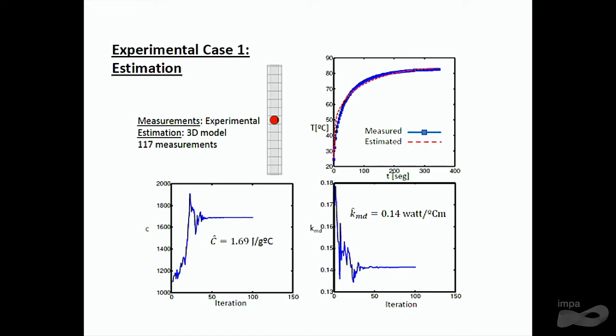The values obtained are close to the ones reported in the literature and the ones we have measured by independent means. This basically corroborates the validity of the model and essentially the assumption that we made, that only the particles that are in the cross section between the beam and the sample are the ones that produce heat.